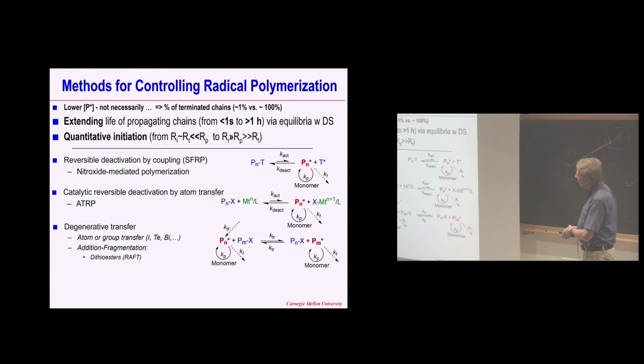So these compounds typically will be organometallic species, or sometimes transition metals like copper or iron or ruthenium, as you will see later, and we call it atom transfer radical process. There is also another possibility, so-called degenerate transfer. So here you could see that equilibrium is very strongly shifted toward dormant species. Equilibrium constant may be 10 to the power minus 9, 10 to the power minus 5, and here equilibrium constant is 1. So whatever you have on the left side and right side is exactly the same.